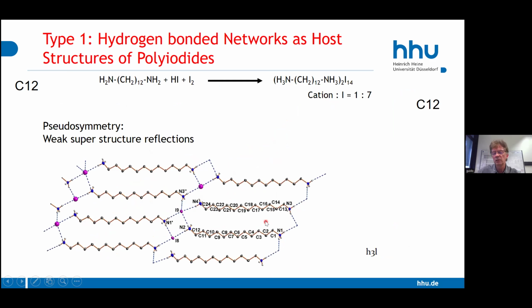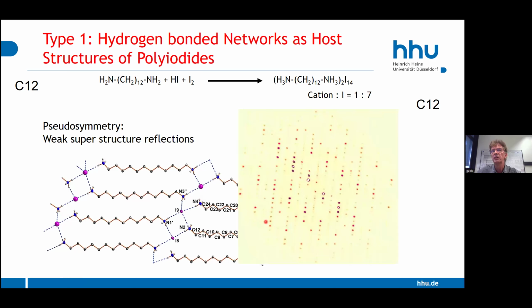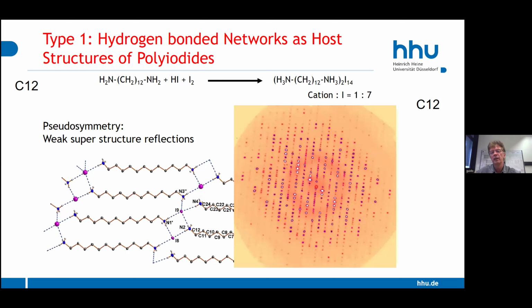And when we do a normal crystal structure determination, which all try to, don't irradiate so long, because the next project is waiting, and perhaps we can make it faster. In the field of polyiodides, it's complicated. If you make a normal structure determination, your picture would look like this. It would simply say, we have a lot of reflections. They are just nicely separated. Only here in the 0 level, you see that there could be something problematic. So for our determinations, we always use really long exposure times or a very intensive source. And then the diffraction pattern looks this way. And only if you harvest all this information also from these weak reflections, you really get the true structure and the full image of all of them.